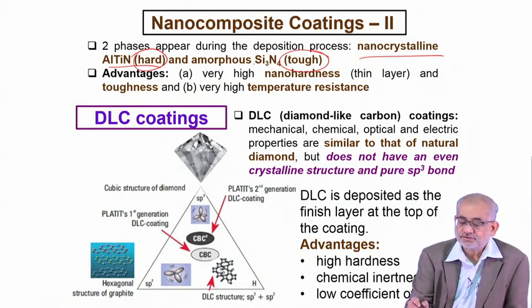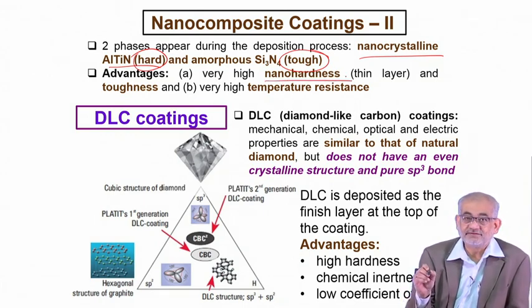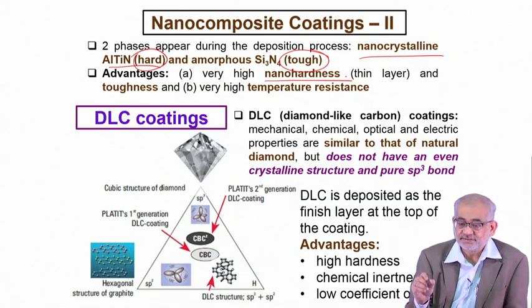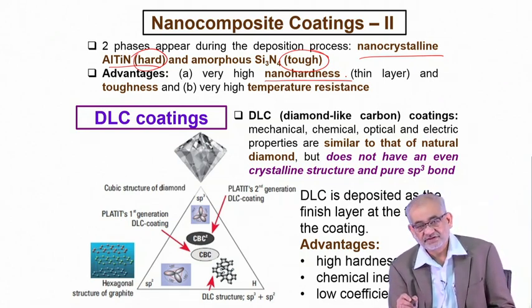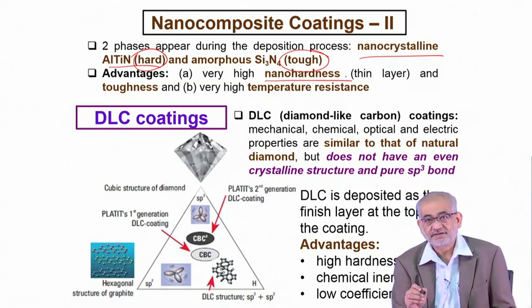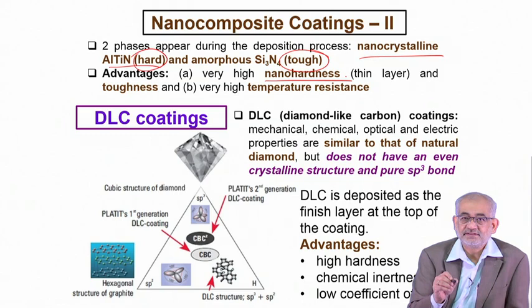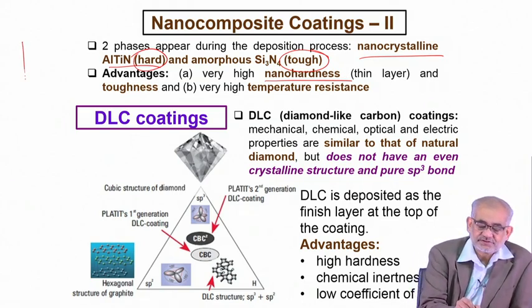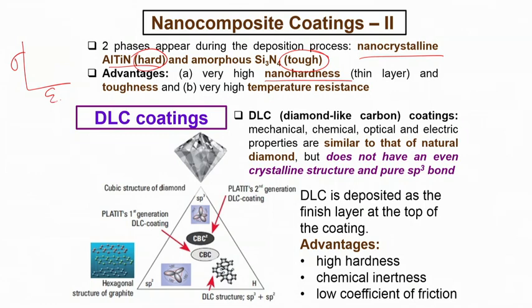So the advantage is that we get very high hardness. In fact, the thickness of the layer is so thin that you actually use a nano indenter with millinewton level of load application. So the range of load that you apply is very small. You indent a very small depth, and when you make such a very thin indentation, you actually can produce a typical stress strain curve for a very limited region. So you have a proportionality limit,